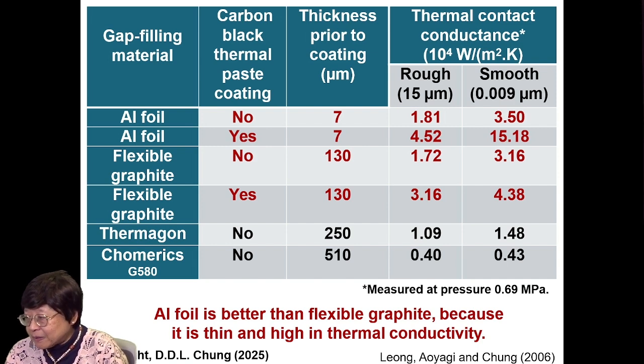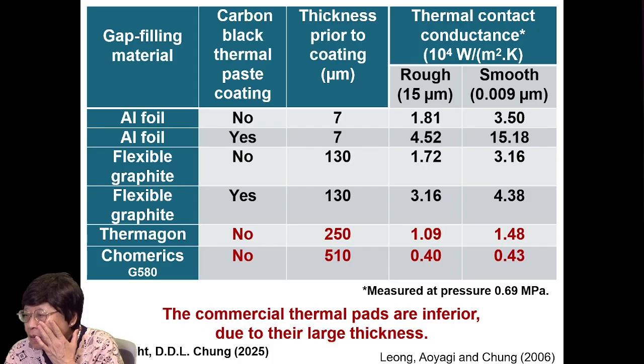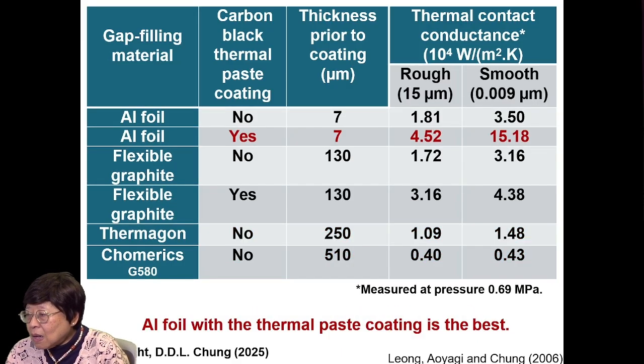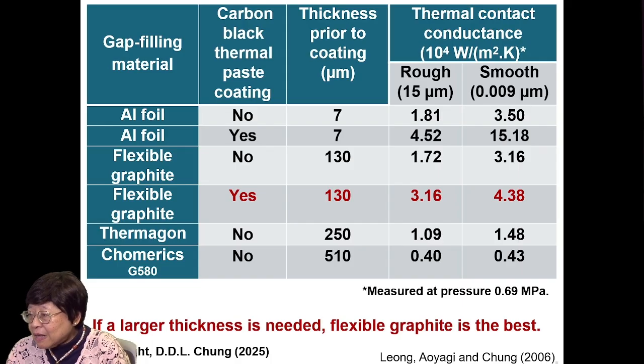The aluminum foil is better than the flexible graphite because it is thin and high in thermal conductivity. For both the rough and smooth surfaces, the aluminum foil is better, whether with or without the carbon black thermal paste coating. The commercial thermal pads, Thermagon and Chomerics, are inferior due to their large thickness. You see the thickness is very large, and that results in very low thermal contact conductance. The aluminum foil with the thermal paste coating is the best in this list. If a larger thickness is needed, flexible graphite is the best.